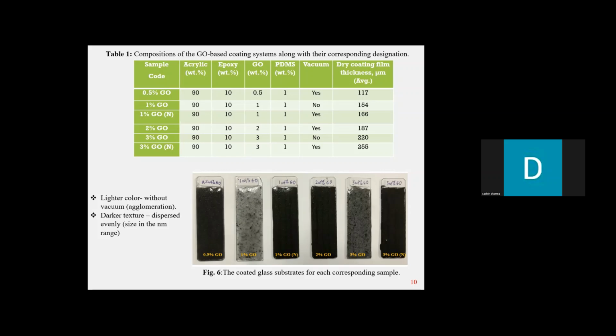How do we ensure that the cross-linking had occurred between both the resins? Here I added IPDA, isophorone diamine, which was calculated based on the ratio of the epoxy.